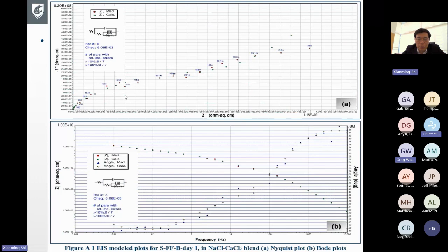Basically, what we find in the end is, from these figures you obtain from the EIS test, you can analyze the interfaces. For instance, here at the top you see a combination of capacitance and resistance. This is a simulation, or so-called equivalent circuit, of the coated metal surface. The first resistance is basically the resistance of the solution, the de-icer solution. And then the second combination, which is the capacitance and resistance, is basically an indication of the coating to de-icer solution interface.